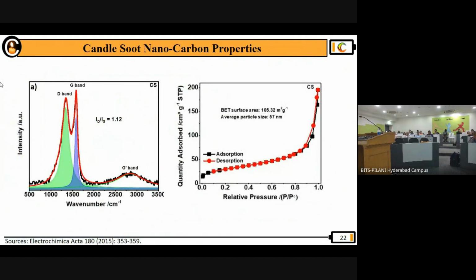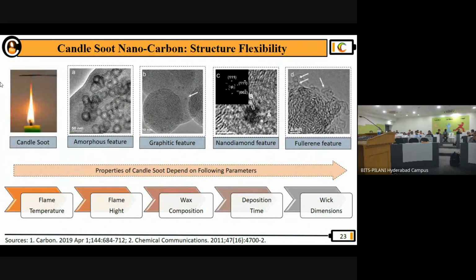When we look at this material, typically the ID by IG ratio is 1.12, which means it's an amorphous carbon, and the surface area of as-collected soot is around 100 meters squared per gram, which is not very great, but we can enhance it in different ways. So as I was mentioning, the same soot can have amorphous features as you collect it, but by different ways you can have graphitic features, nanodiamond features, and fullerene features also embedded in the same material. It depends on flame temperature, flame height, the wax composition, how long you are depositing, and the wick dimensions. So these are very simple parameters you can vary to change your material depending on your final interest.